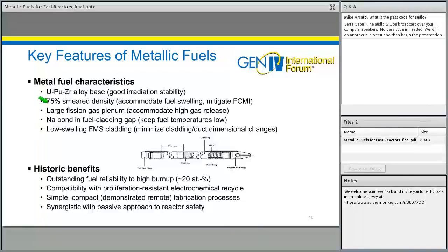Now, with that big of a gap in metallic fuels, you have to put a liquid metal bond in the fuel cladding gap, and typically that's been sodium. So liquid sodium in the fuel cladding gap is the bond, keeps the fuel temperatures low, provides a lot of other benefits. It's just generally a good thing, but it's an added complication in fabrication. Metallic fuel, because of the large amount of swelling that happens early on, those gas bubbles interconnect very early in life, and then the metallic fuel will begin releasing most of its fission gas, on the order of 80%.